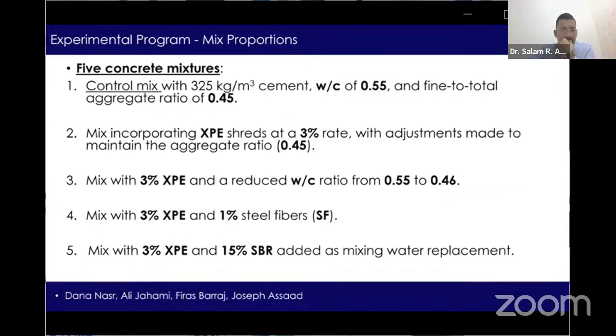Moving now to the mix proportions. 5 concrete mixtures are tested in this work. One, the control mix with no XPE, which contained 325 kilograms per meter cube cement, a water to cement ratio of 0.55, and a fine to total aggregate ratio of 0.45.